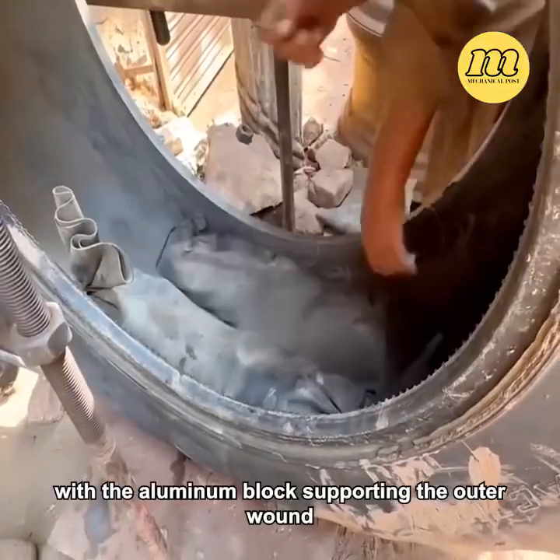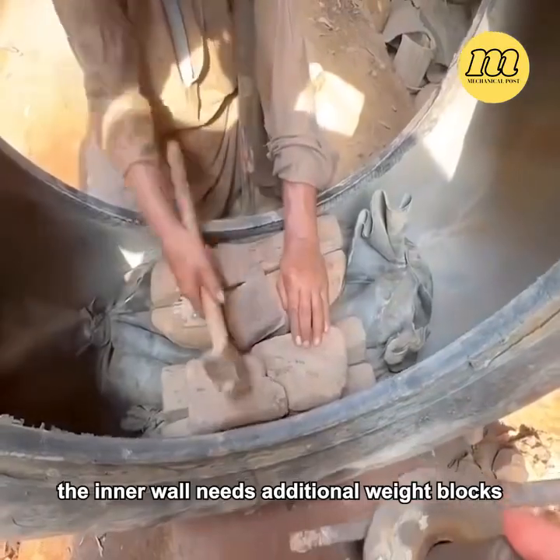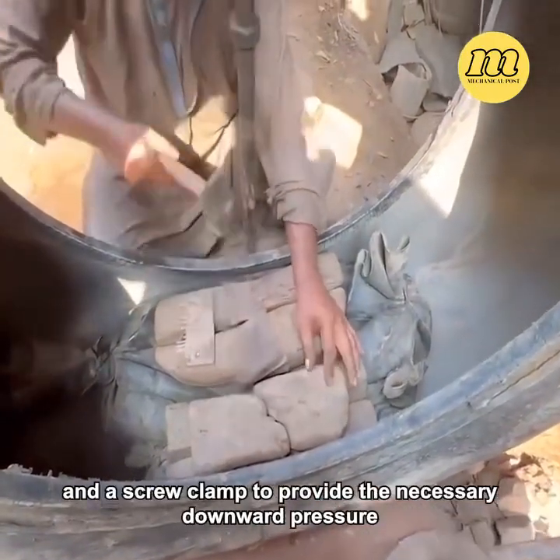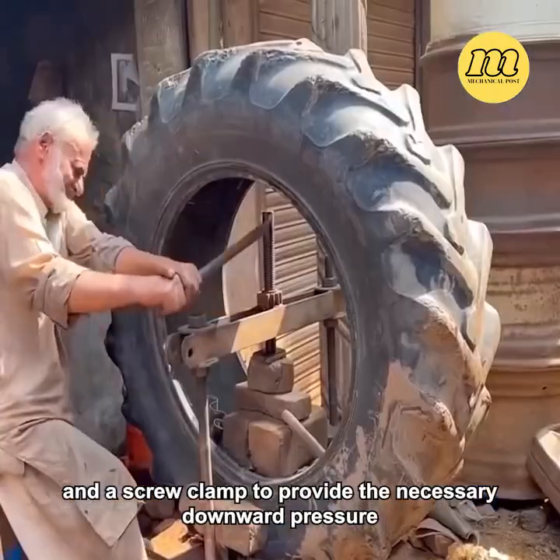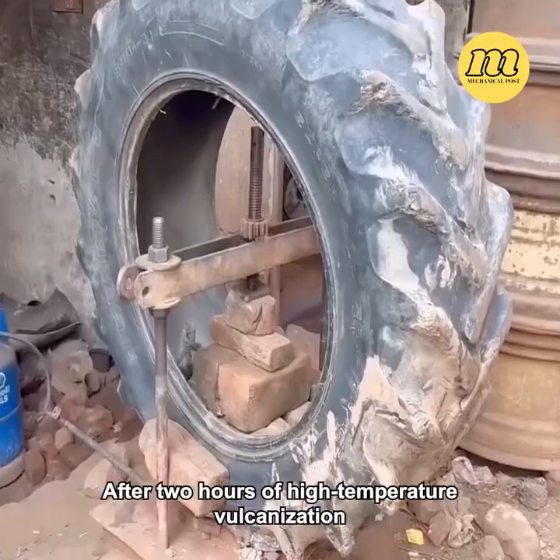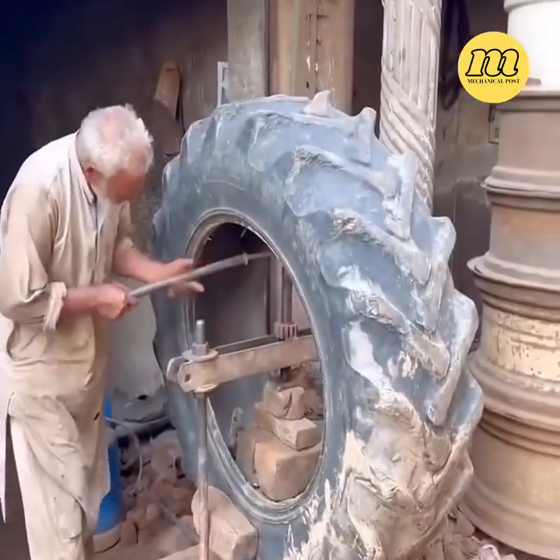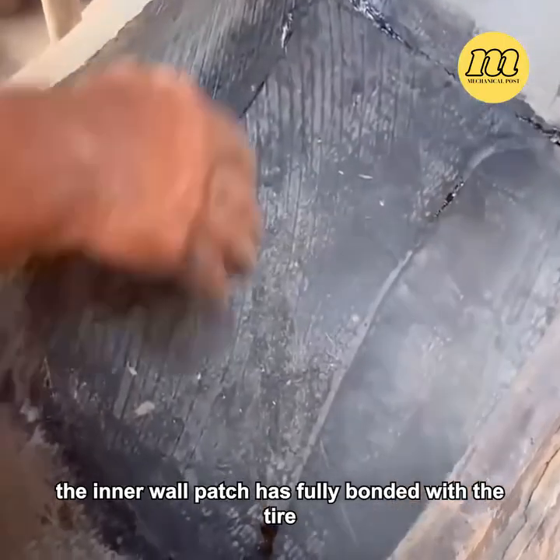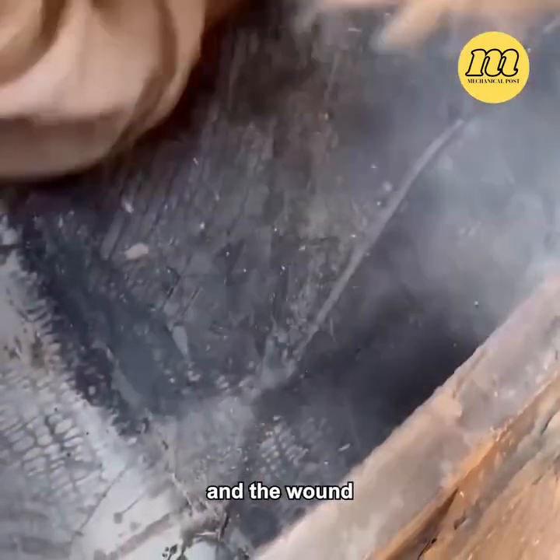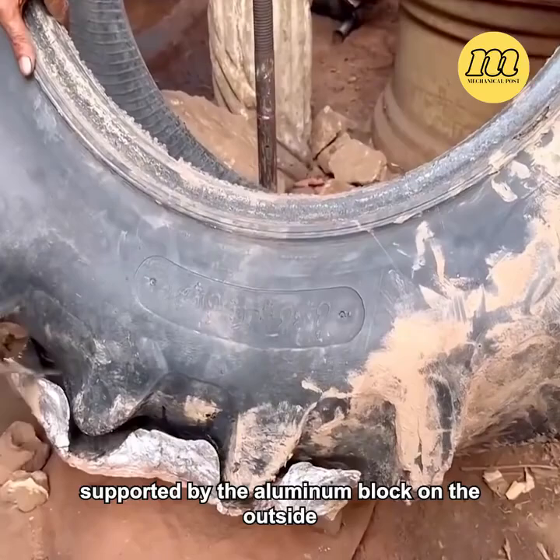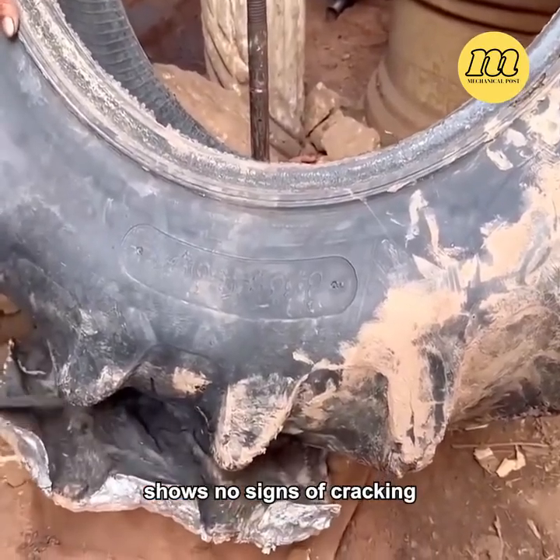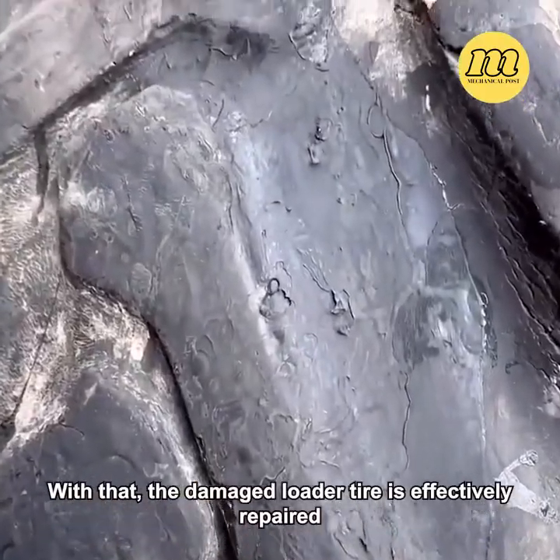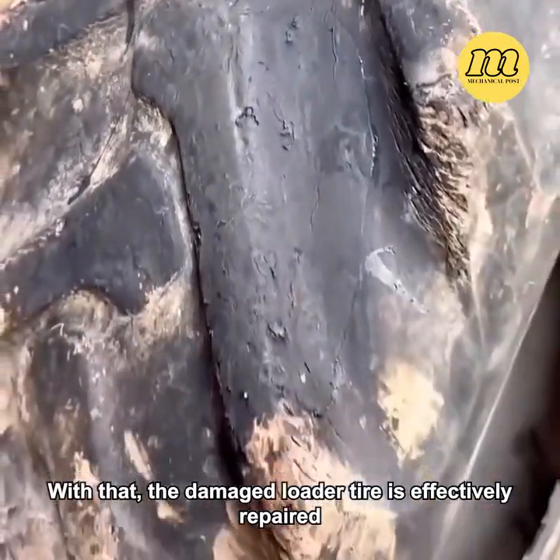With the aluminum block supporting the outer wound, the inner wall needs additional weight blocks and a screw clamp to provide the necessary downward pressure. After 2 hours of high-temperature vulcanization, the inner wall patch has fully bonded with the tire, and the wound, supported by the aluminum block on the outside, shows no signs of cracking. With that, the damaged loader tire is effectively repaired.